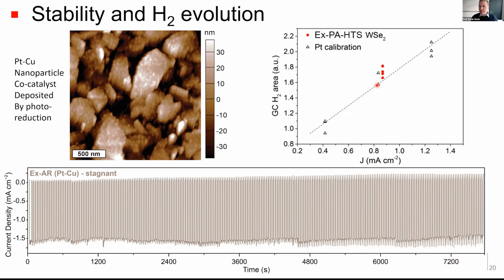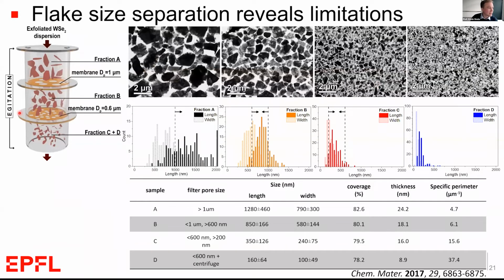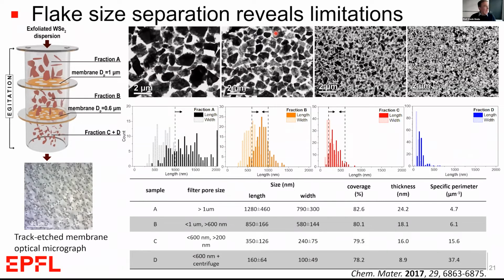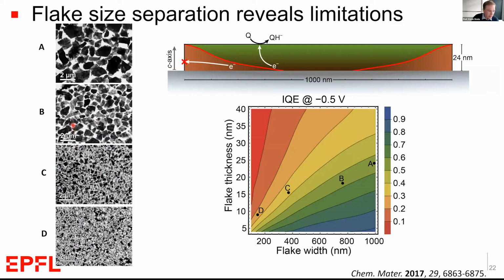Now, since we've demonstrated this, we've done a lot more work in trying to understand the limitations of these nanoflake-based devices. One way to do that is to separate the flakes into different sizes and test these different size flakes that are produced by this ultrasonic method. I don't have time to go through all of the details, but you can see in this paper what we found: there was a nice link between the flake thickness and the flake width that really limits the performance of these ultrasonically produced devices.